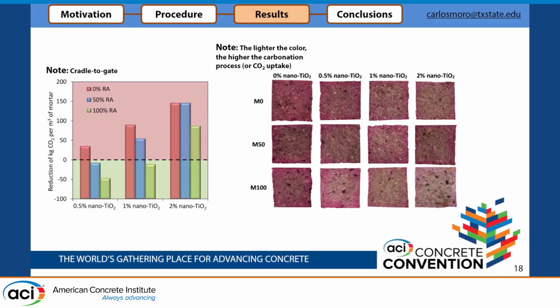So we also saw that if we use the phenolphthalein test, in this case it measures the carbonation that the samples could have. And I show, going down, that means that we use more recycled aggregate, and going to the right, that means that we use more nano titanium dioxide. And we can see a trend here that if we use more recycled aggregate and more nano titanium dioxide, the carbonation is faster and faster. That means that we are promoting CO2 capture during the service life. What does this mean compared to the left figure? That means that we still have a chance.